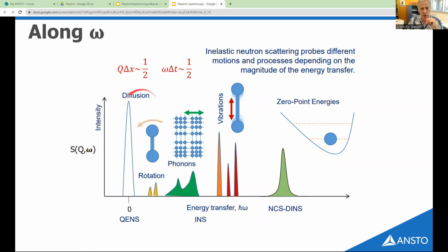Now, in the case of QENS, quasi-elastic neutron scattering, this is really looking at diffusion effects. So there, I'm going to read this because I'm going to have a cheat sheet here. In the case of EMU, it has micro-eV resolution. In the case of Pelican, I believe, and Richard Moll is here, so he can correct me, 50 to 350 micro-eV resolution.